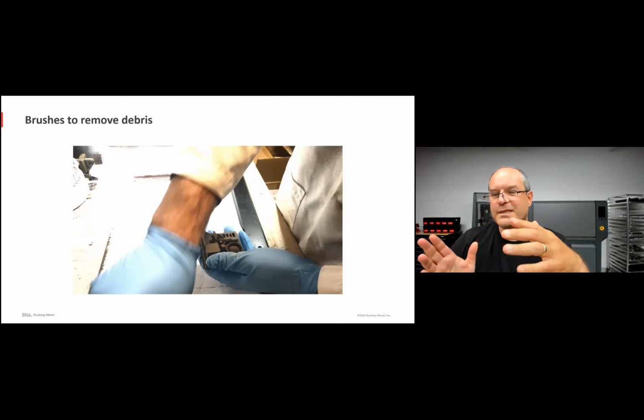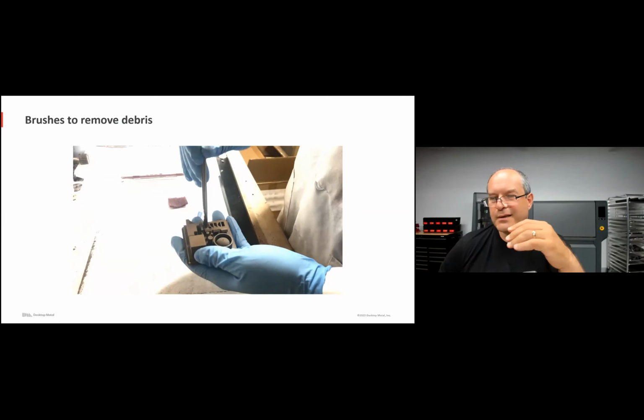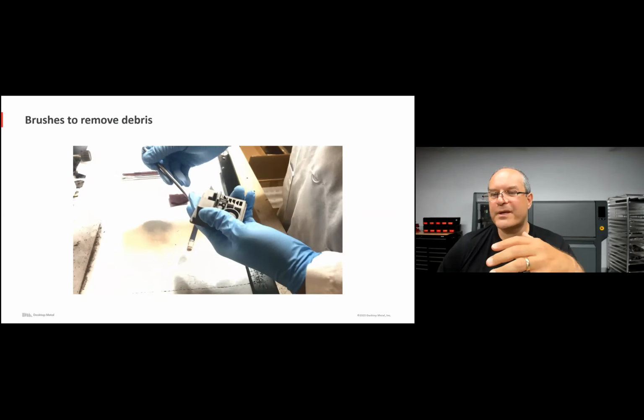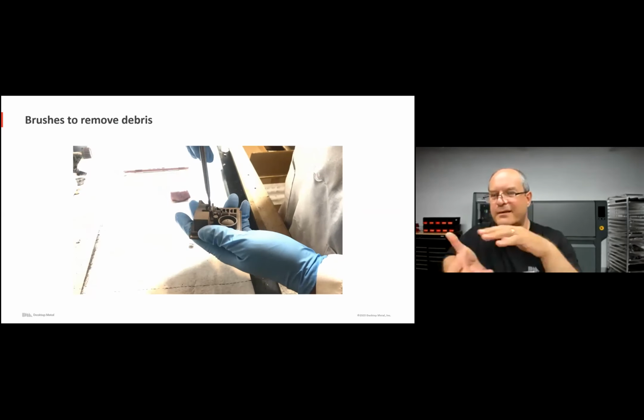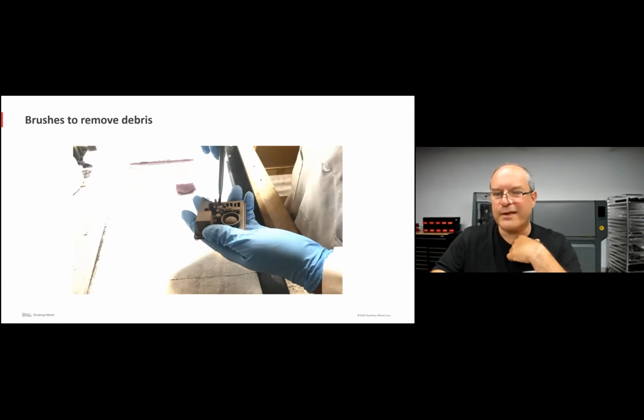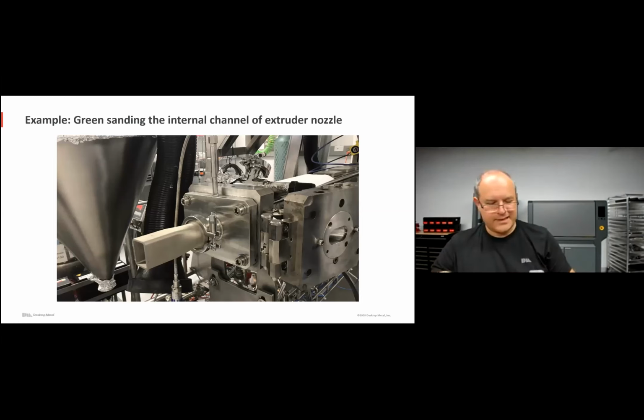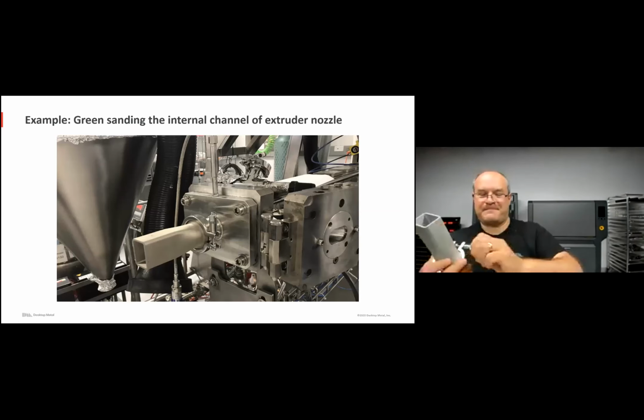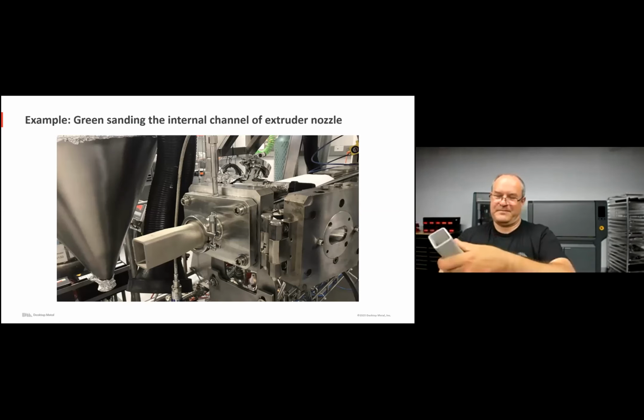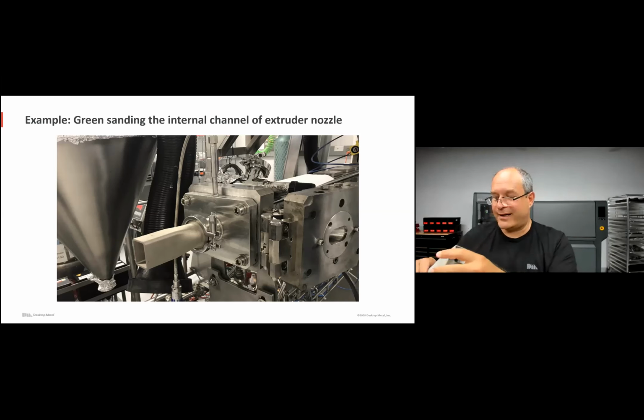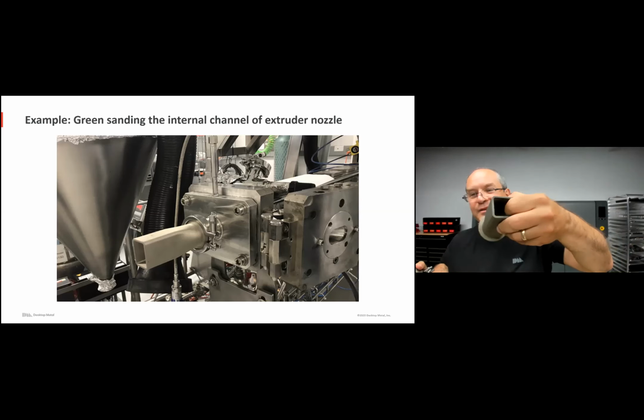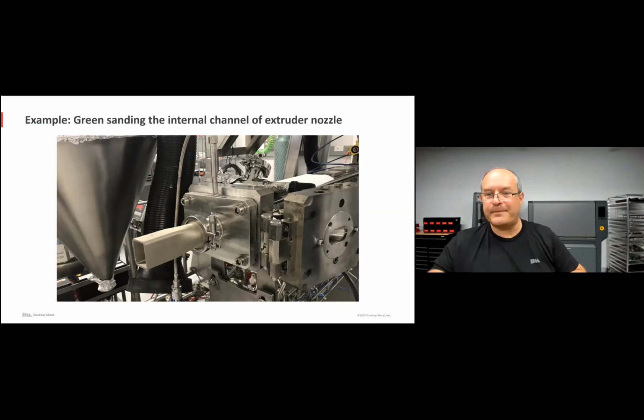Depending on how much debris there is, this is mostly necessary not for the mass production shop system, but more for the studio system, a kind of extrusion-based shape creation, where this might be a useful technique. So that's brushes. And the example, this is that very nozzle. Here's the interface. So with a gasket comes on through here, the twin screw extruder pushes the ceramic slurry, and the less friction inside the channel, the better. So the green sanding was great as a way to get a remarkably smooth internal surface.